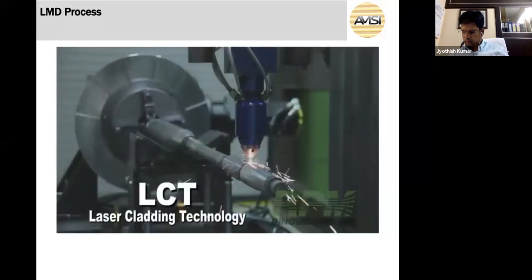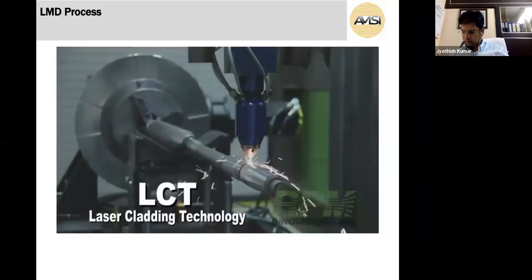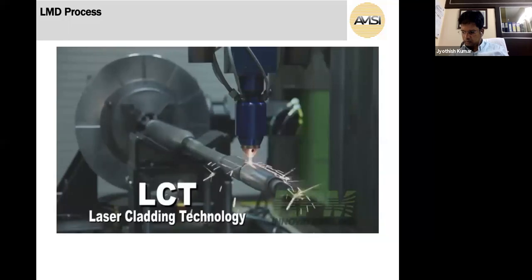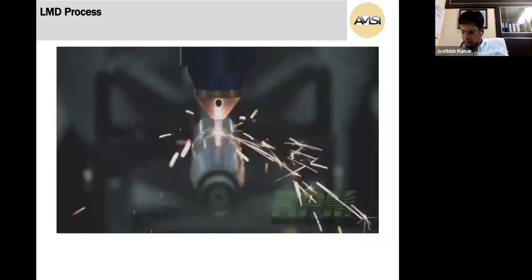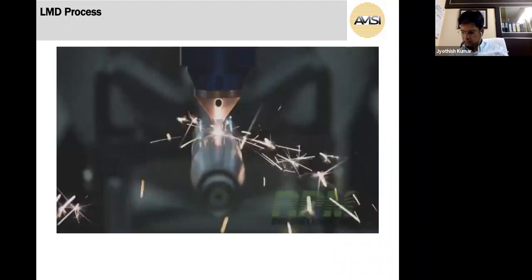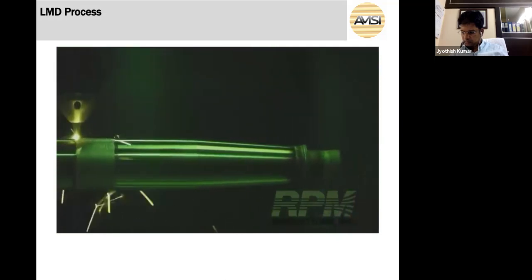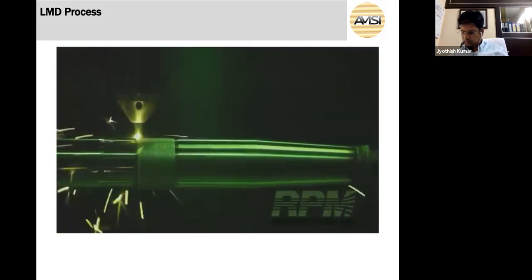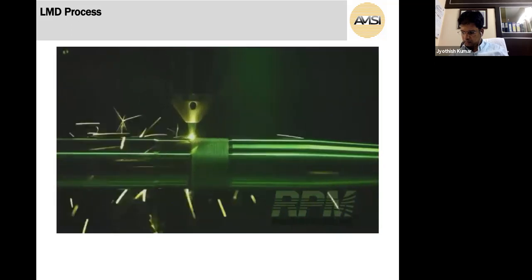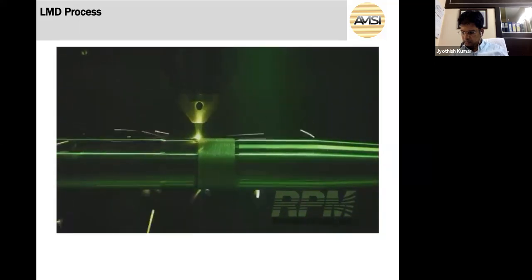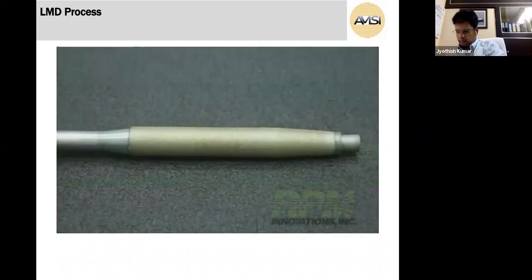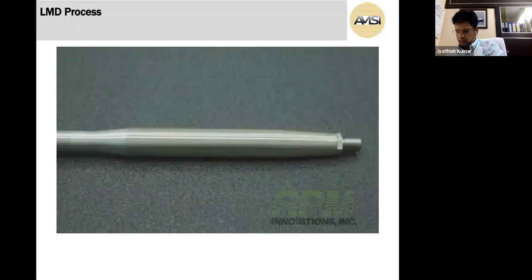LCT, which stands for Laser Cladding Technology, is also a very effective process for performing repairs on heat-sensitive materials, such as 4340 or pH-grade stainless steels. After the wear area is identified and a tool path is generated, the repair is initiated. By carefully controlling laser power and travel speeds, the heat effect and dilution zones are minimized. The result is a very low stress input into the part, which results in very low distortion.